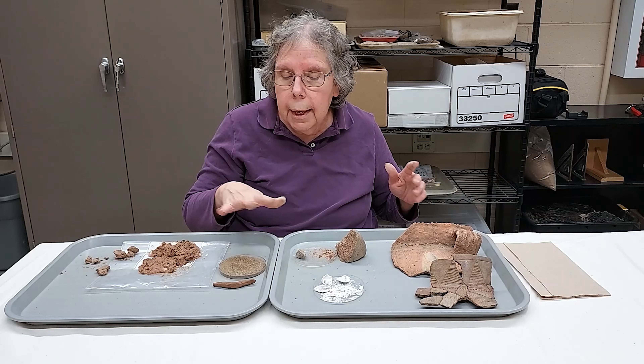The temper in the pottery is very helpful for archaeologists to date it. This particular piece of pottery is about 2,000 years old — it's very thick, which is another indication that it's pretty old, and it also has very coarse crushed rock in it. This is a good example of that variation between clay and the crushed rock temper. Other sherds might have finer temper, but there's still going to be that crushed rock, still having that variation, particularly in the cross section.